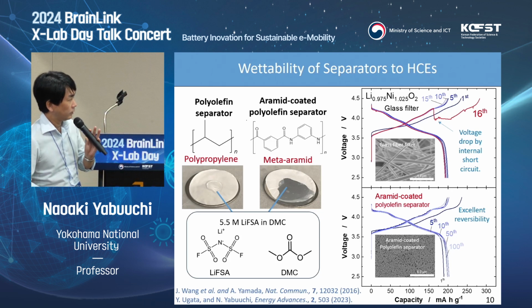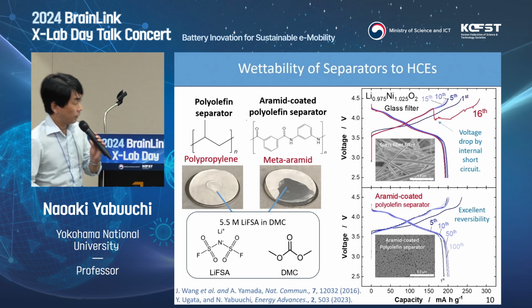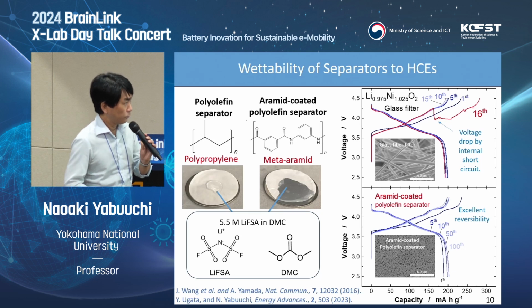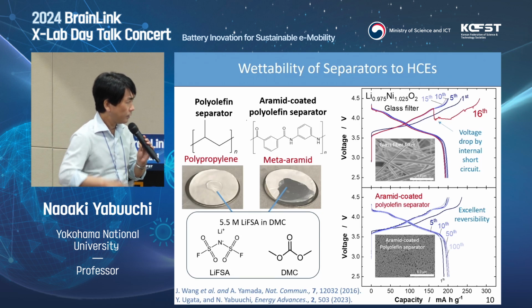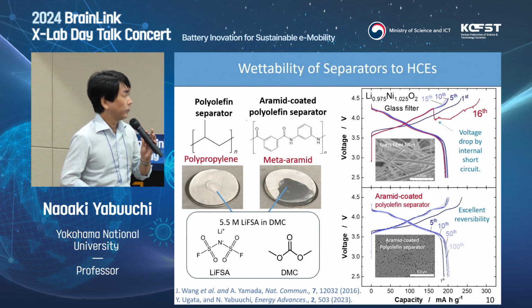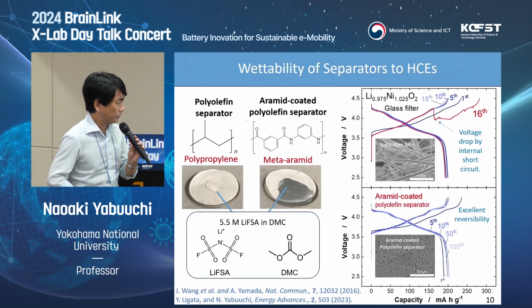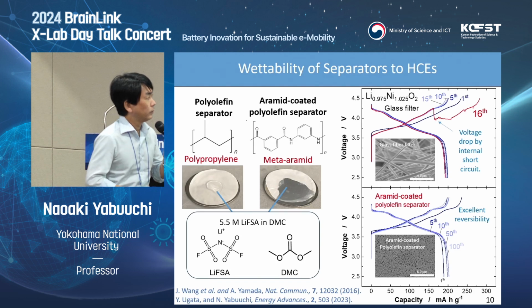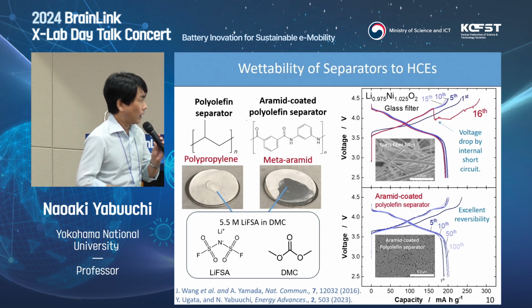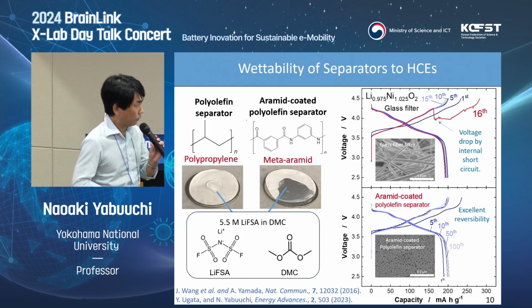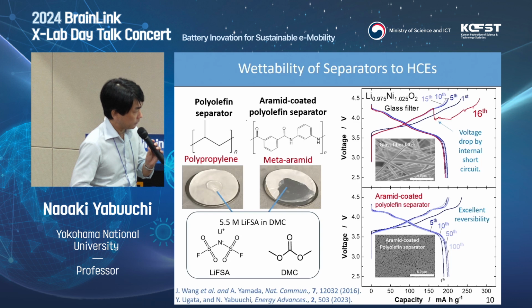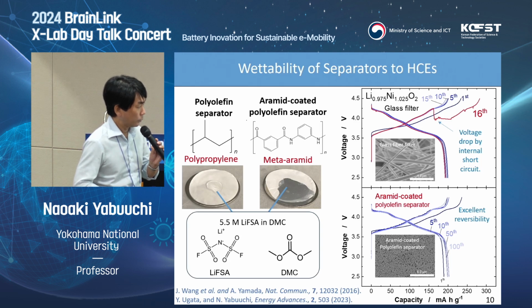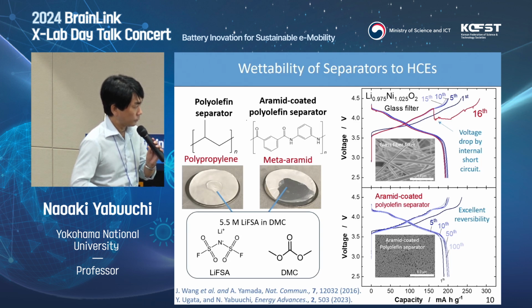So therefore, it is difficult to use a highly concentrated electrolyte solution for high areal capacities. So recently, we published one paper in Energy Advances. We found that a meta-aramid coated polyolefin separator is wettable to highly concentrated electrolyte solution.